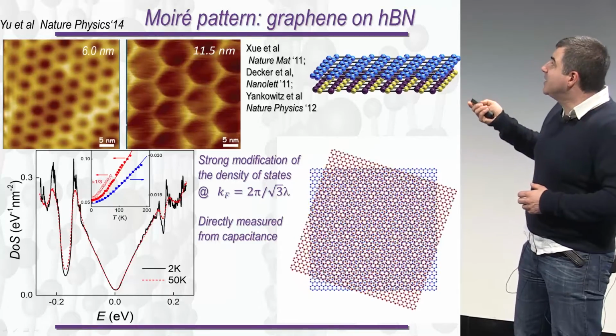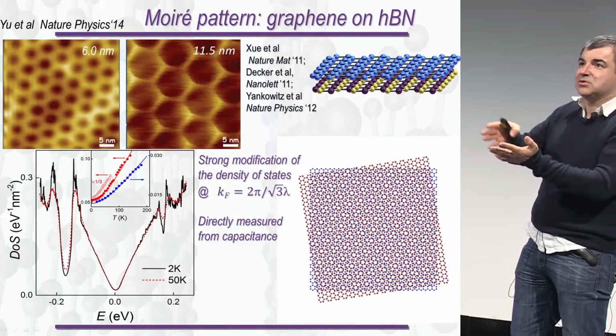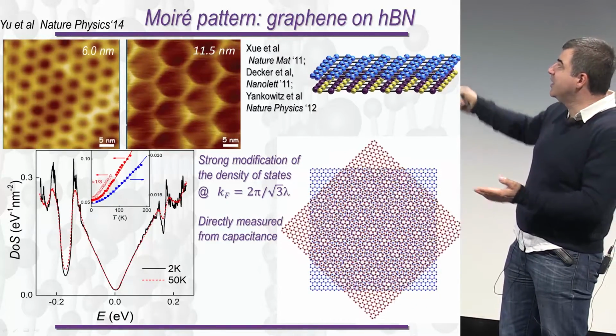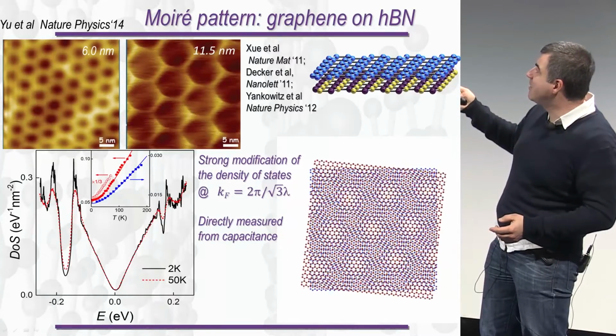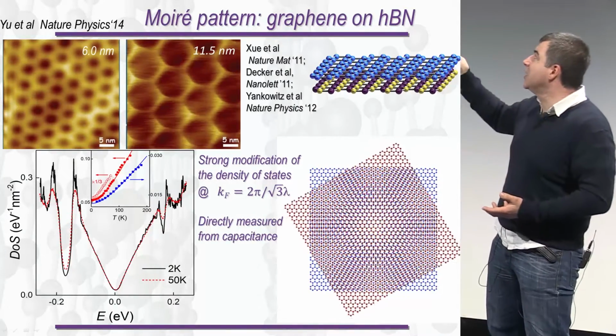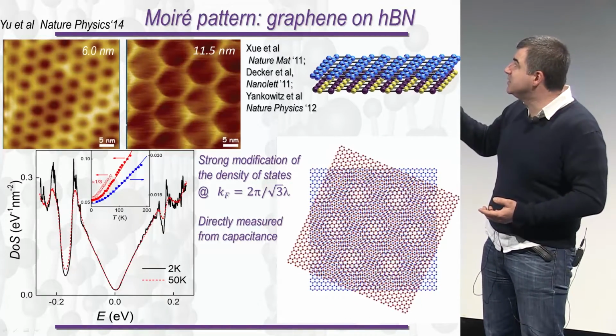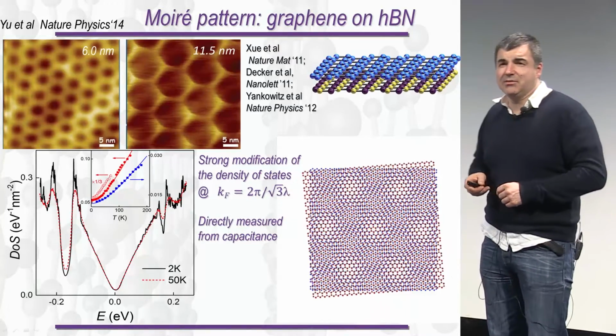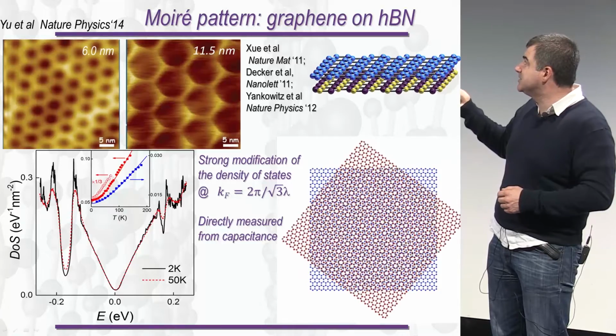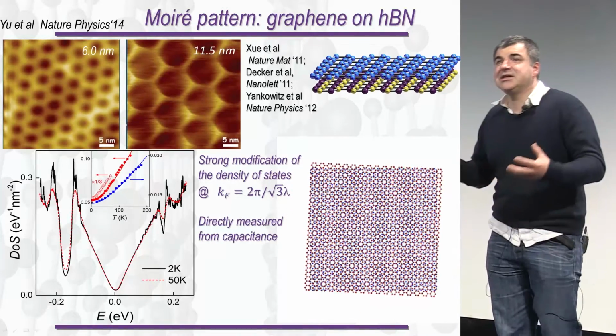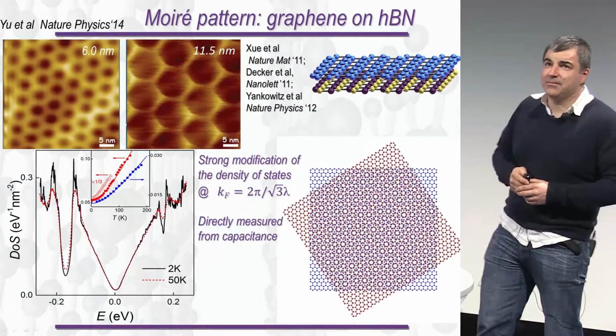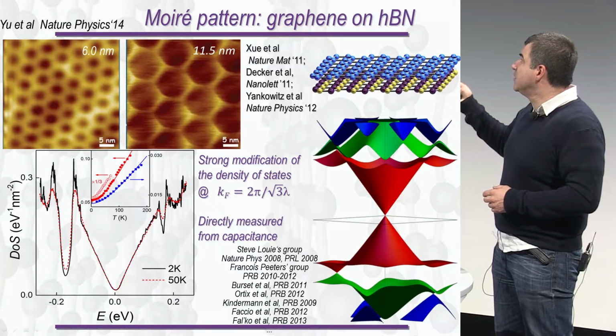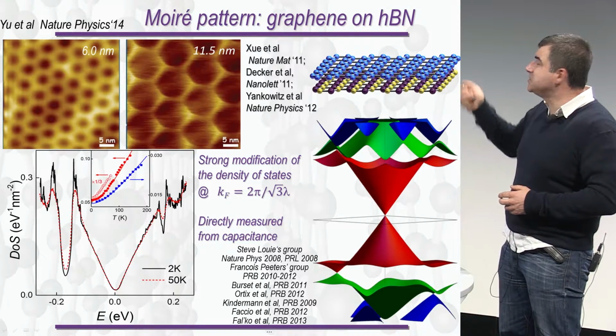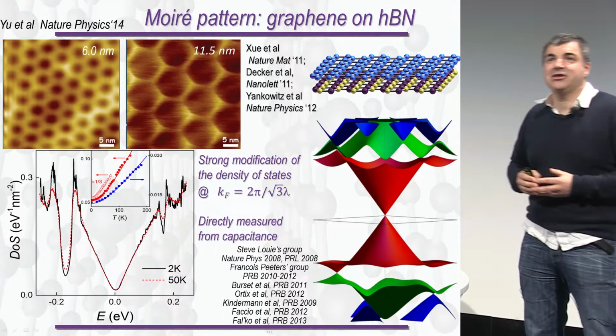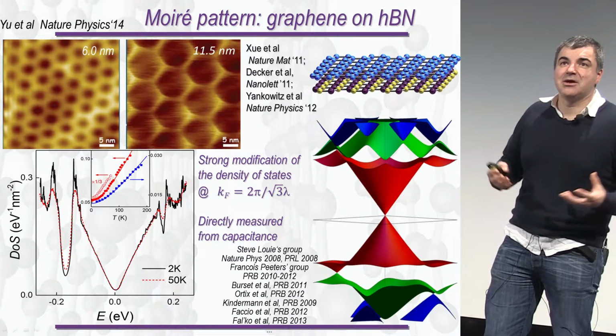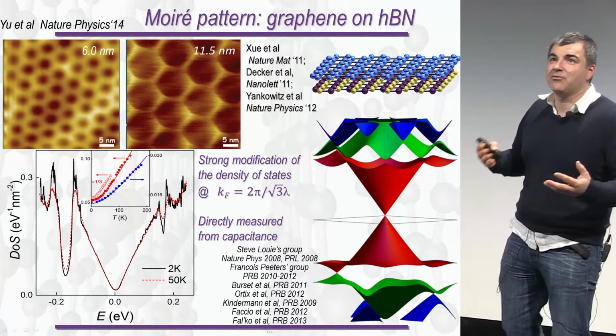what I get at the end is a periodic potential for electrons in graphene. It's like you take two crystals with periodic patterns, you put one on top of the other, and if you rotate them slightly, what you see is the so-called moiré pattern, and that's exactly what happens for our graphene on boron nitride, and that's what you see in those STM images. So these patterns are not atoms, it is the same moiré pattern which I showed you here, and this gives me a very specific property of the electronic structure. Basically, apart from this cone which I always had, I get some smaller cones a little bit outside at different energies, which is quite an interesting object by itself. So I will get a new type of quasi-particles.